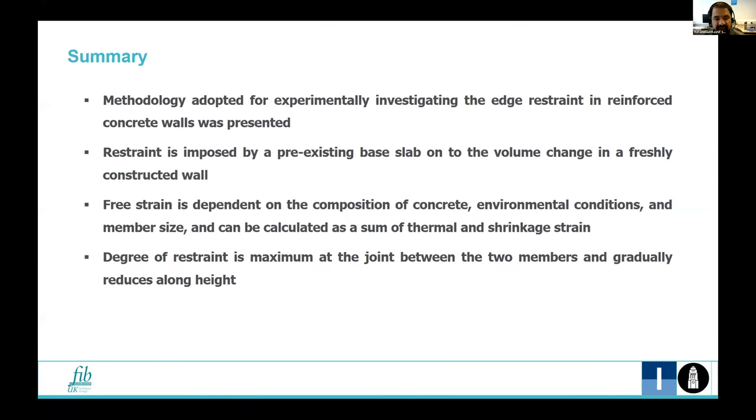To summarize, the methodology adopted for experimentally investigating the edge restraint in reinforced concrete walls has been presented. Restraint is imposed by pre-existing base slab onto the volume change occurring in the freshly constructed wall. Free strain is dependent on the composition of concrete, the environmental conditions and member sizes, and can be calculated as a sum of thermal and shrinkage strain. The degree of restraint is maximum at the joint between the two members and gradually reduces along the height.